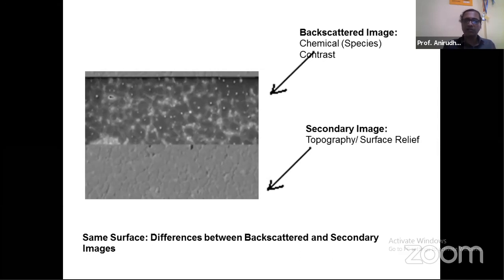So you can use a backscattered image to differentiate between areas belonging to different species on your tribological interface. Whereas if you are interested in finding the relief, that means distribution of surface features which would get reflected in terms of peaks and valleys on your surface, then it is advisable that we use the secondary image. So when you are using the SEM, there would be a selector switch, whether you should be using your backscattered detector or your secondary detector. Most of you would have done that. So by a judicious selection, you can investigate the features of the topography and surface relief. At the same time, when you switch to the other mode, the backscattered one, you will get some information related to the distribution of these species over this surface.